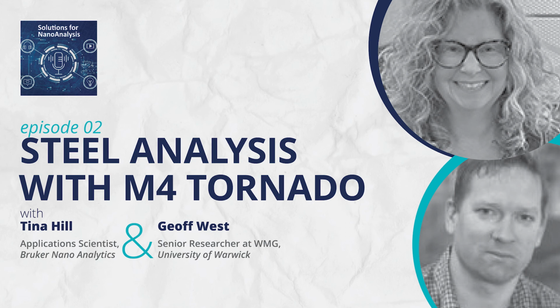So we tend to prepare our samples, even the big blocks. We wouldn't want to stick it in a microscope and do EBSD on it, but we try and prepare it. We don't just grind it and then stick it in. We try and get the preparation to be as good as we can in a reasonable time period, just so that we haven't got a smearing effect, and that we are giving ourselves a chance with the Bragg diffraction. But the quality of the Bragg diffraction we get does seem to be variable, and we don't understand fully what we need to do to make it.